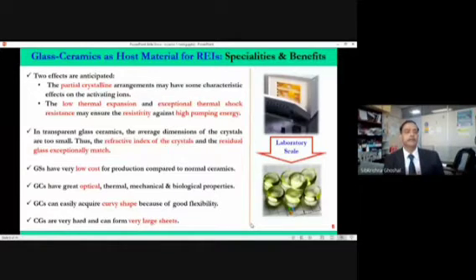Another reason why we use these glass ceramics is that the benefits come from other aspects. They are partially crystalline, so the crystallinity plays a role. Remember one thing, the rare earth will not show any effect by itself. It chooses a particular host and it shows different effects. Why is the host important? Because depending on the symmetry and asymmetry of the local environment, the local structure of the host, of the crystal or the ceramic or the glass, the effect of the rare earth would be entirely different.